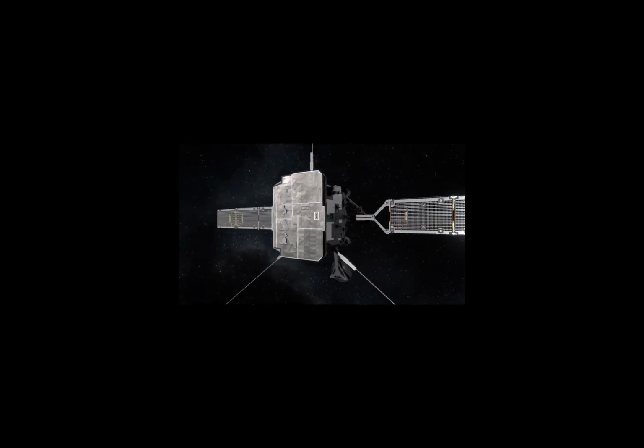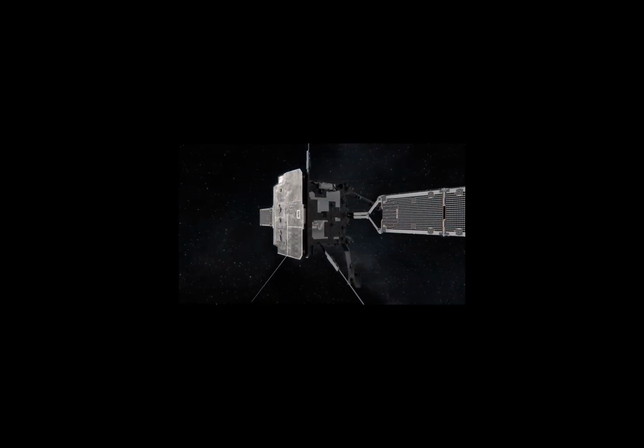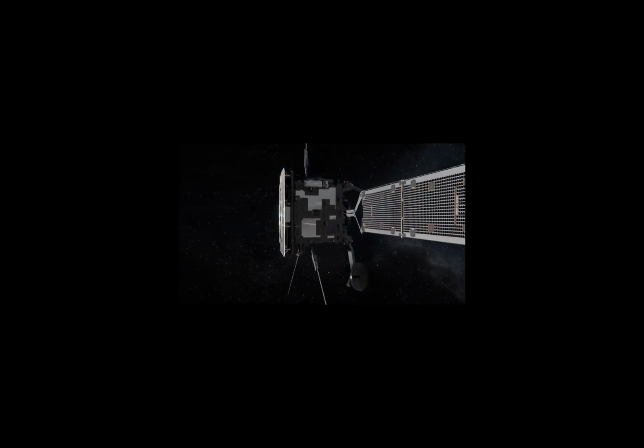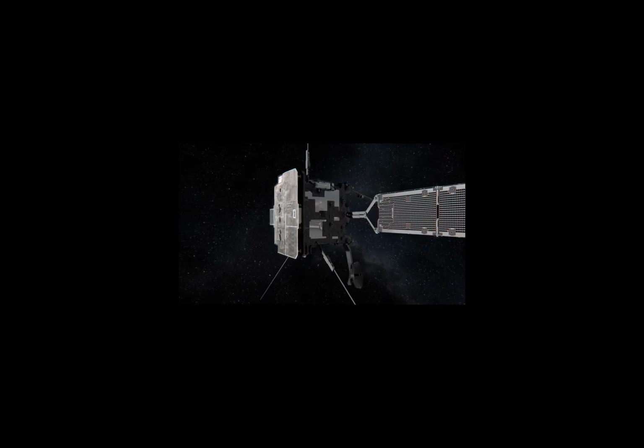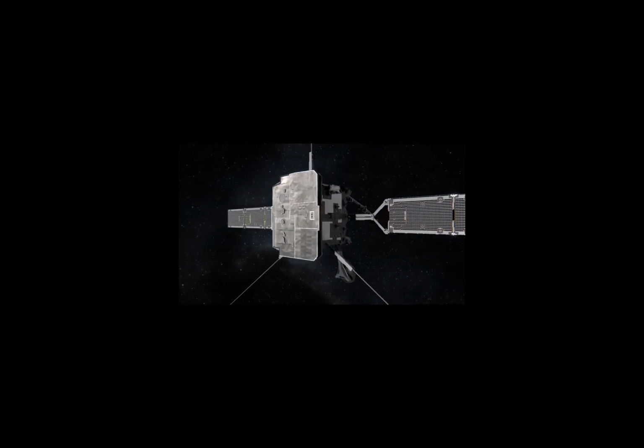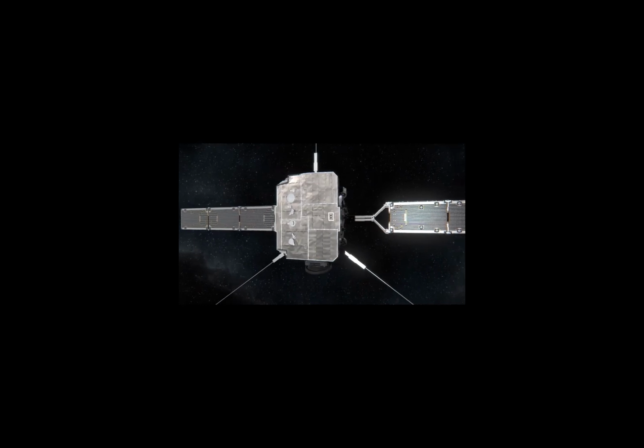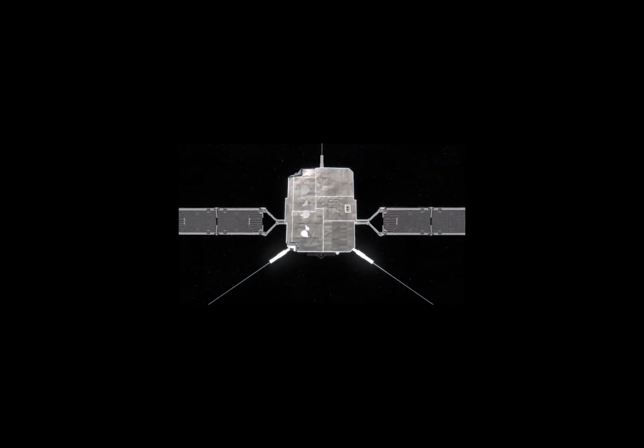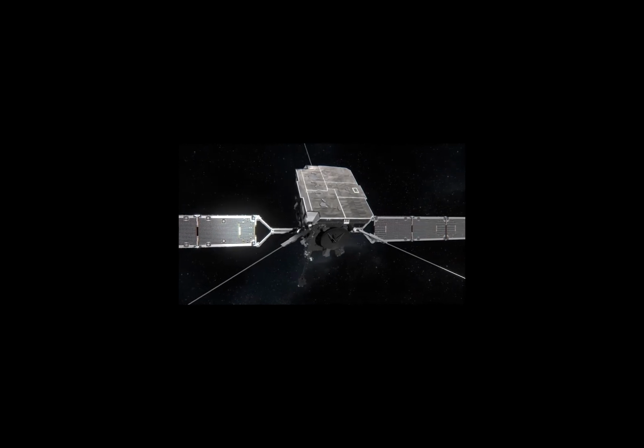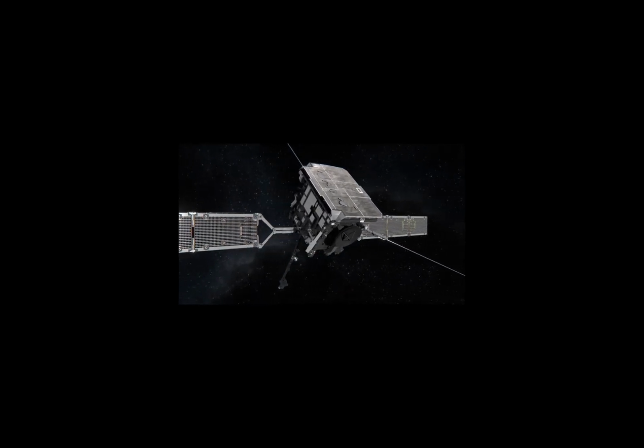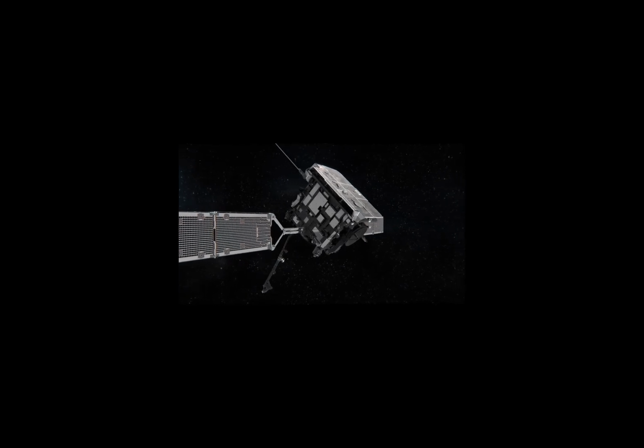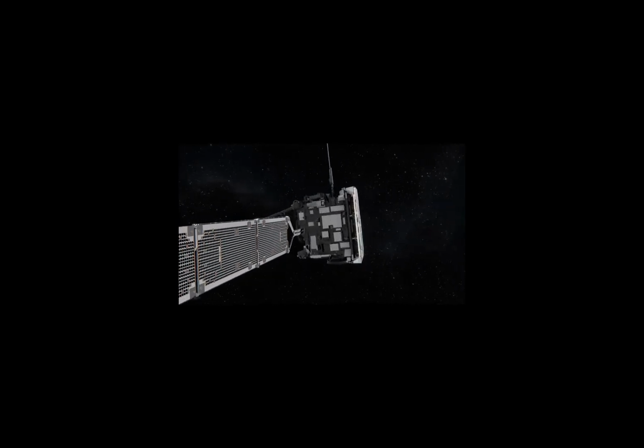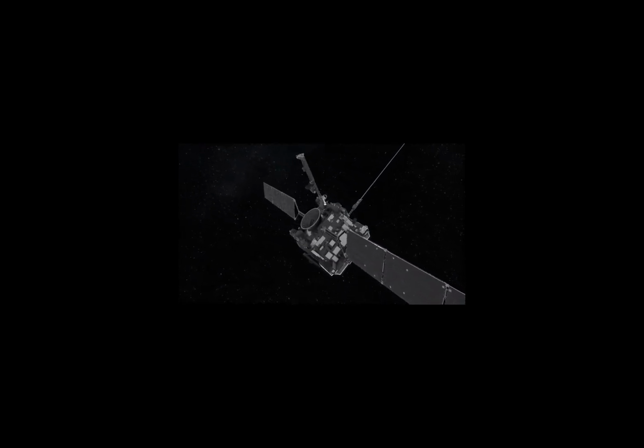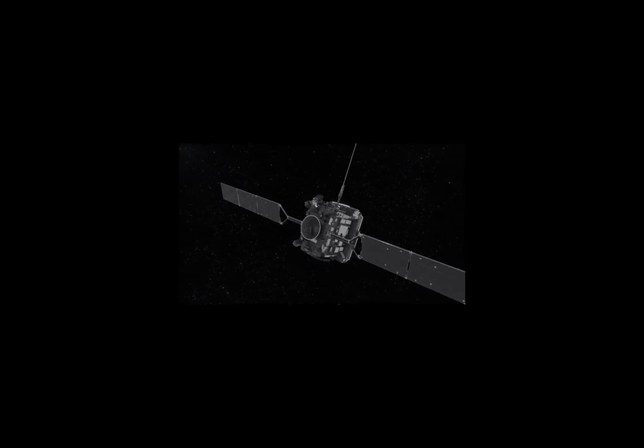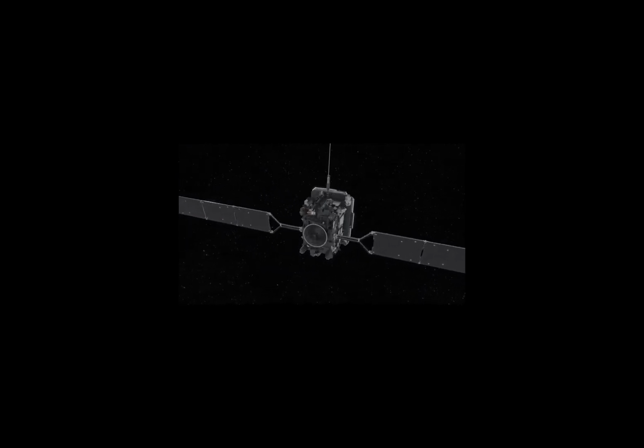When stowed, each antenna is kept in place by 3 hold down and release mechanisms, HDRMs, that when opened in sequence release the device. For each HDRM to release, shape memory alloy based frangibolt actuators and hinges activate, allowing 2 stowing flanges guided by bearings and driven to their open position by springs. As some SMAs are activated at a certain temperature, the temperatures of these components are highly regulated to avoid premature deployment, achieved using multi-layer insulation shells around the frangibolts.